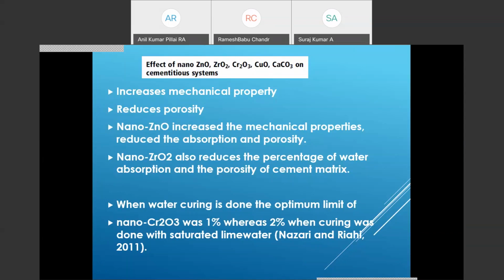When water curing is done, the optimum limit of nano chromium oxide was 1%, whereas 2% was when the curing was done with saturated lime water. So this is a research output where the curing was with saturated lime water. So the optimum limit was about 2% when curing is done with saturated lime water, whereas it is only 1% when normal curing is done.